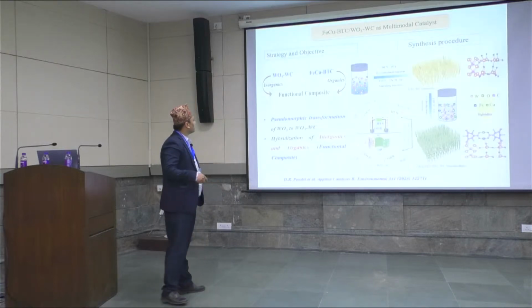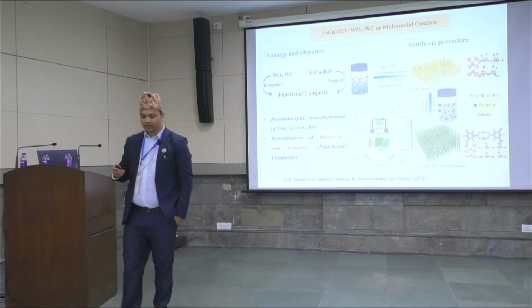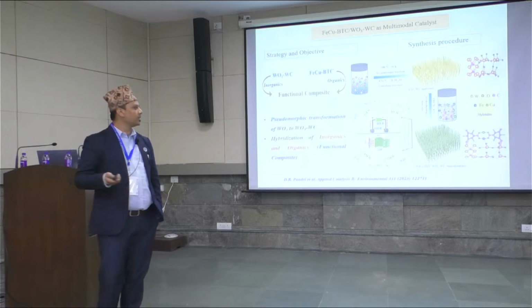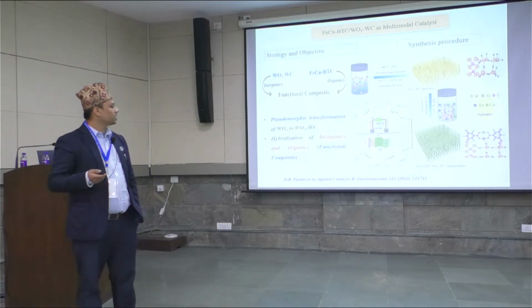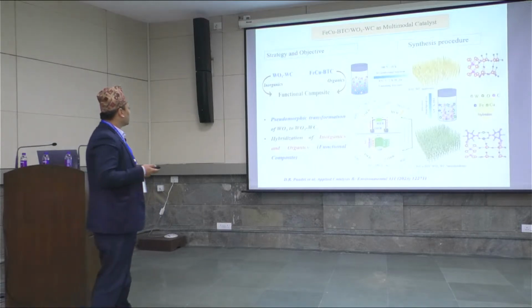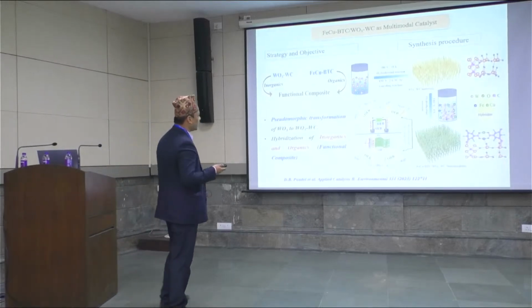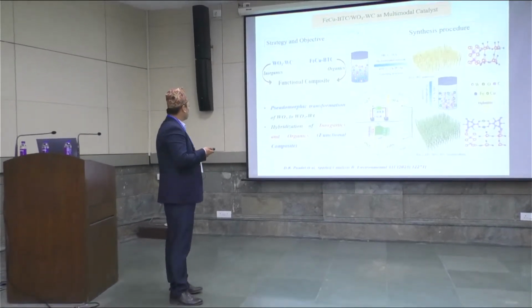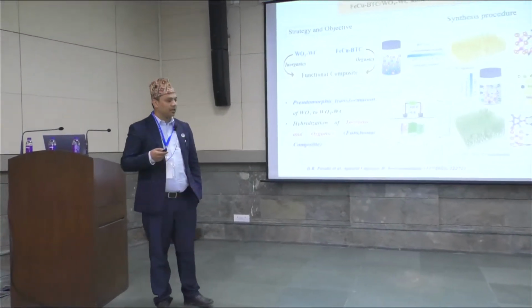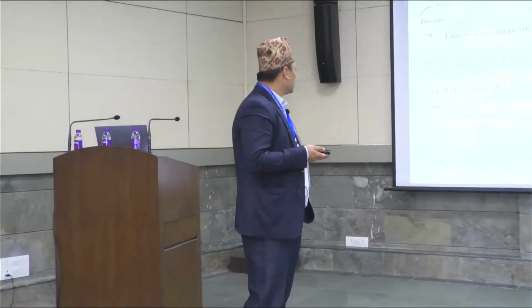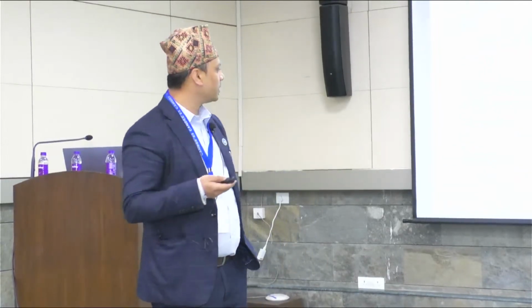This is our strategy. The electrocatalytic activity can be enhanced by making the functional composite, where we prepare WO3, tungsten trioxide, by a very simple hydrothermal method, and the pseudomorphic transformation by the annealing process in the presence of iron. The tungsten oxide is partially converted into tungsten carbide, and the heterostructure is formed, WO3 and WC.